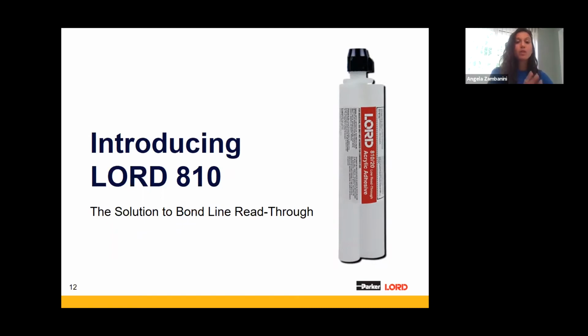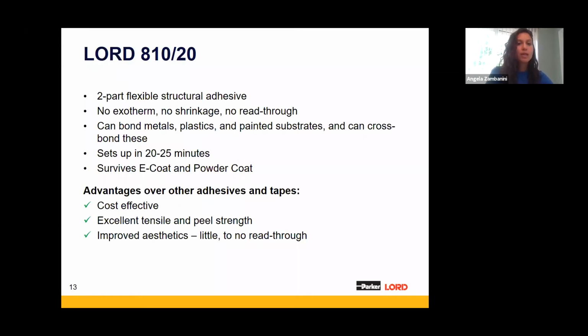Now I'd like to introduce the Lord 810, which is the solution for bondline read-through. As of today, the Lord 810 is the only solution on the market that specifically targets and works to reduce or even eliminate bondline read-through. The Lord 810 is a two-part flexible adhesive. It's nearly 3 times as flexible as some of our other traditional acrylics, which helps it move and expand with ACM and other thin gauge materials, even materials with a different CTE, meaning they expand and contract at different rates. That high flexibility is why the Lord 810 is so successful at eliminating read-through.